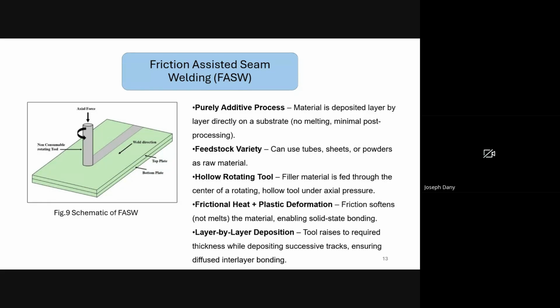similar to the way we do in friction surfacing, we can also perform multi-track seam welding. Coming to additive manufacturing using FASW, here we join multiple layers, either in a single-track or a multi-track manner. Although studies are limited, this method has been successfully used for materials like aluminum 6061, titanium Ti6Al4V, and stainless steel 304, in both similar and dissimilar combinations, for thicknesses ranging from 0.5 mm to 5 mm.